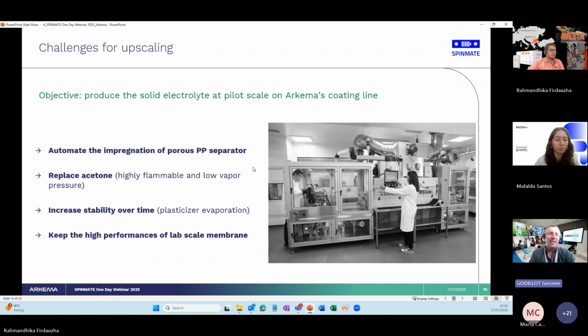Then the solvent used was acetone. It's highly flammable, so it cannot be used in industry for safety reasons. And it also has a high vapor pressure, which makes it very difficult to use at industrial scale, because it evaporates very quickly, and the composition of the formulation evolves too quickly to be used for long coating runs.